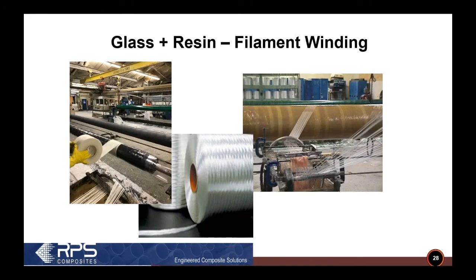So when it comes to making pipe, you can actually make pipe the same way. You could saturate the glass by hand and apply it to the mold. What you're seeing on the left-hand side is a person who has taken the chopped strand mat and is applying the corrosion barrier by hand. They've saturated the resin, put some wet resin on the mold there, and they're going to spiral on some chopped strand mat to put on the corrosion barrier in the piping.